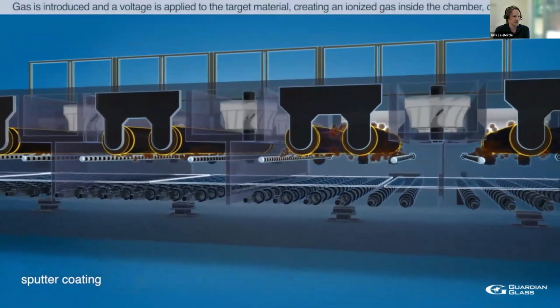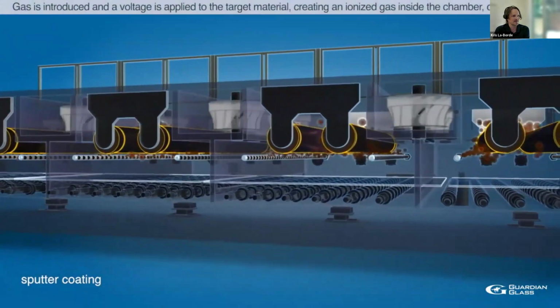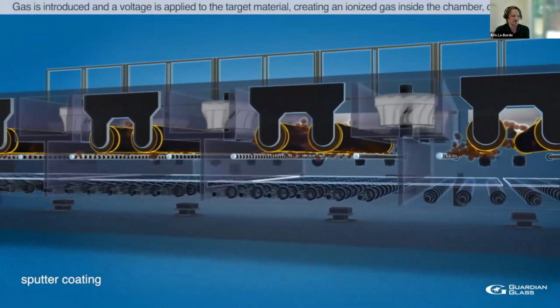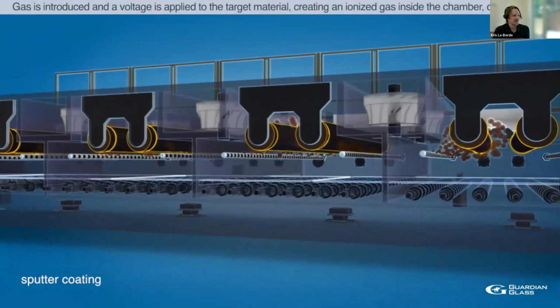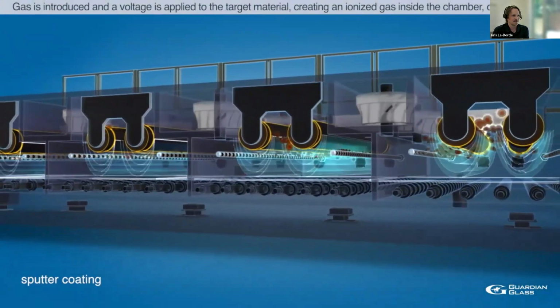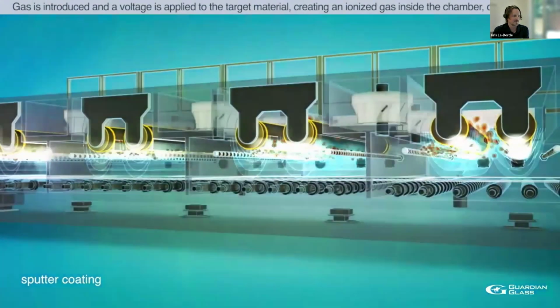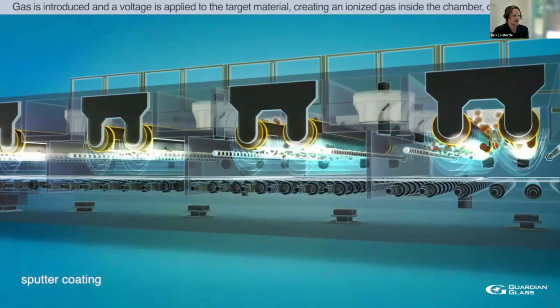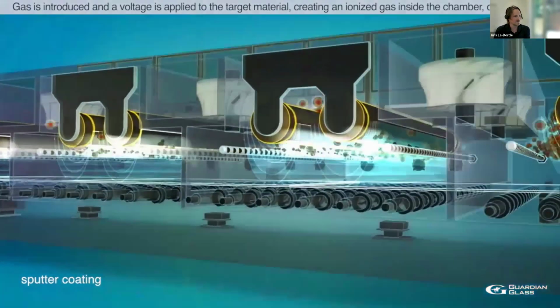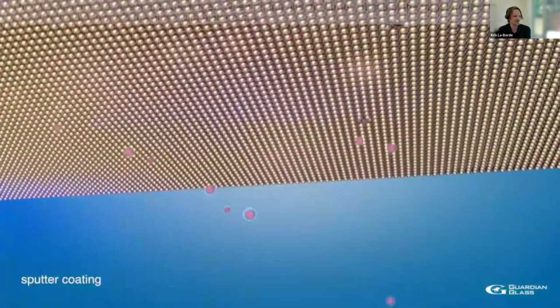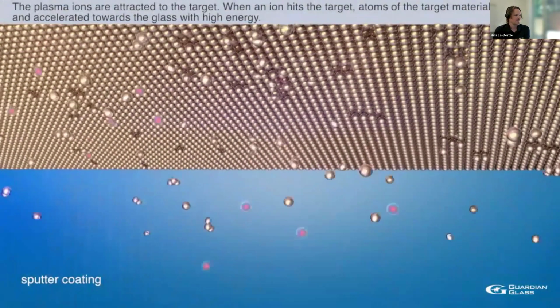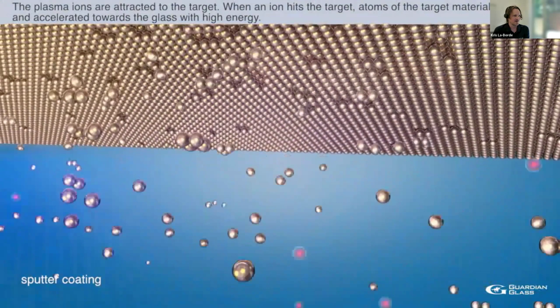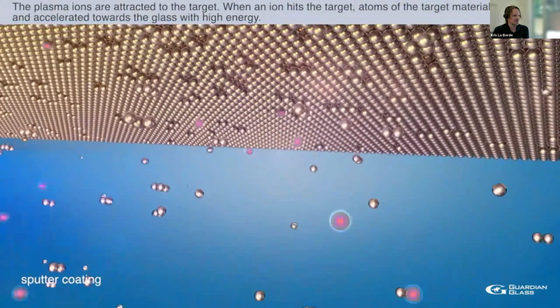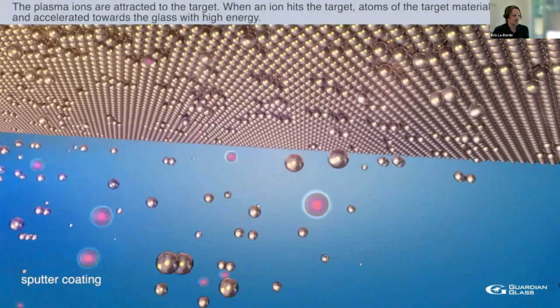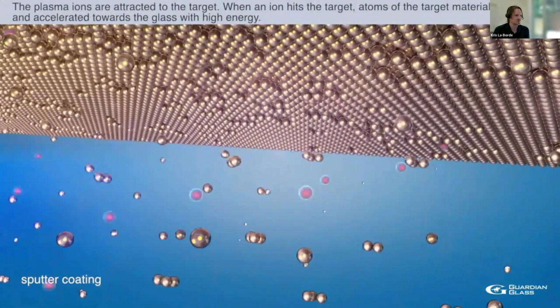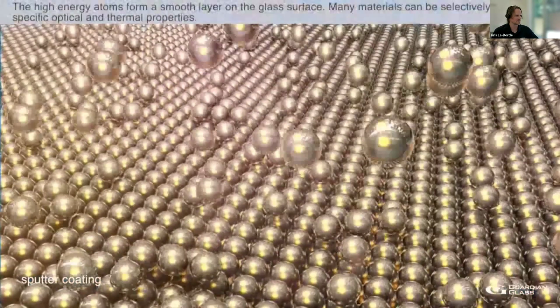And this is what gives you that uniform, very flat, I think it's a 1/5000th of a millimeter thick layer. We call these stacks, and depending on the type of coating you want, will alter that recipe. You may hear the terms single silver, double silver, triple silver. Triple silver is kind of where we are at the limitations of getting low E coatings to do what we can do. We've kind of squeezed as much as we can out of low E coatings.